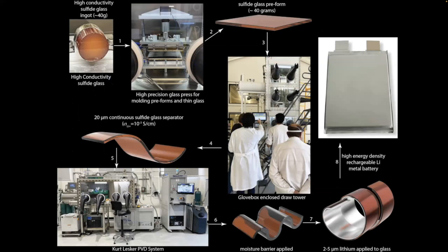And then if we get back to the overall flow of how we go from ingot to thin glass, it looks something like this. We start with a bar of glass. That is then taken into a precision molding press, which molds the glass into a preform. The preform is then transferred to a draw tower. Again, that's all happening in our lab in Berkeley. And the draw tower can draw thin glass. We put a moisture barrier on the glass. That then is coated with lithium. And then we build cells and pouch cells from those components.